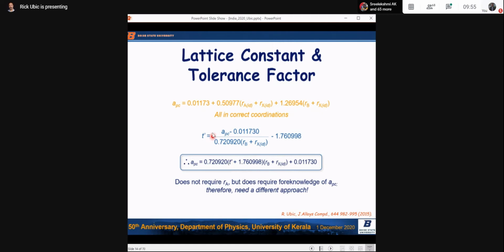To get T prime, we need the lattice constant. So the problem here is that we don't need R_A. So the problem of what's the vacancy size goes away. We don't need to know R_A, but we do need to know the lattice constant. So we can't use this as a predictive approach. We can check things, but unless we already know T prime by experimentally measuring the lattice constant, we don't know enough to use this equation. So we need a different approach.